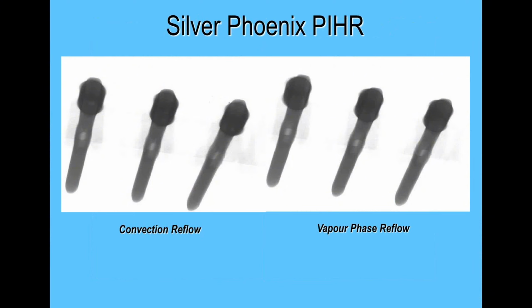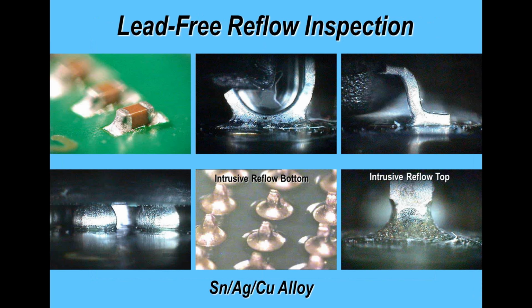Here we've got some perfectly good reflow solder joints, again using lead-free on silver finish, and these are intrusive reflow joints. You've got 100% fill, topside fillets visible on the pins also. And again, just some other representative solder joints. These are all reflowed with SAC alloy. So you've got some traditional joints, some intrusive reflow joints with SAC alloy. These were all reflow soldered with convection in air.